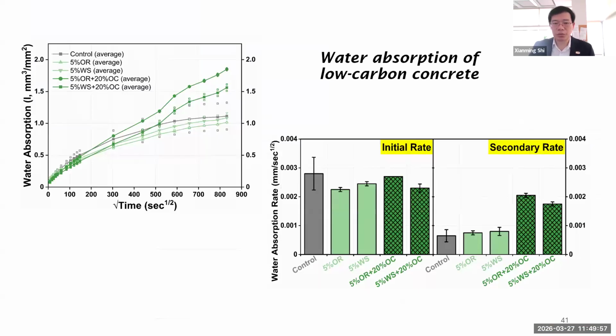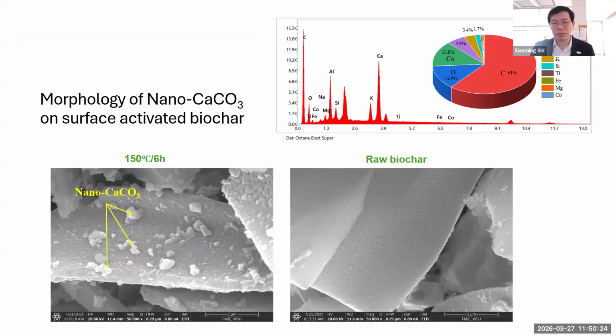Now, water absorption, again, in this case, the initial rate, as you can see here, is not too bad. It's basically comparable with the control, in some cases even slightly lower. But the secondary rate, in some cases, especially when you incorporate too much sand replacement by biochar, does increase. So again, there are tools to reduce this kind of water absorption if needed.